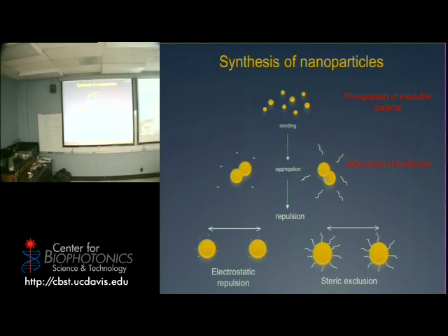Thermodynamically, they are not really stable, and their natural tendency is to aggregate and form larger crystals and essentially crash out of solution. But if you do the synthesis in the presence of some sort of surfactant, which could be an actual molecule, like a polymer, a long acyclic chain or not, or it could be the solvent, for example, that gives charge. As these little seeds start aggregating, the solvent, or ions in the solvent, or molecules that you add start adsorbing on the surface.